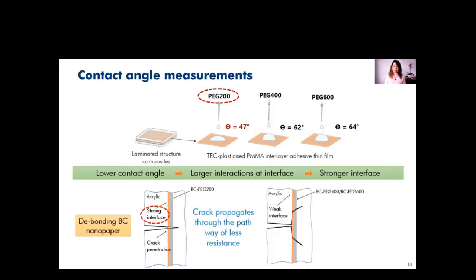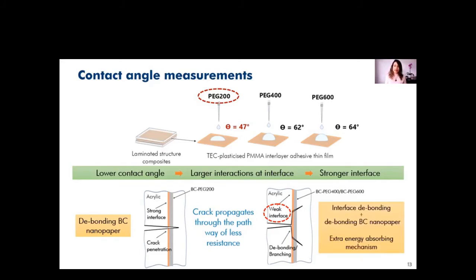In the case of the 400 and 600 systems, the interface is weaker. So when the crack arrives at the interface, it will debond the interface because the crack will propagate the easy way, and then it will branch and penetrate the paper. In this system, there is interface debonding plus debonding of the BC nanopaper, which just means there is an extra energy absorbing mechanism. That explains the higher impact strength of the composites containing the PEG 400 and 600 BC